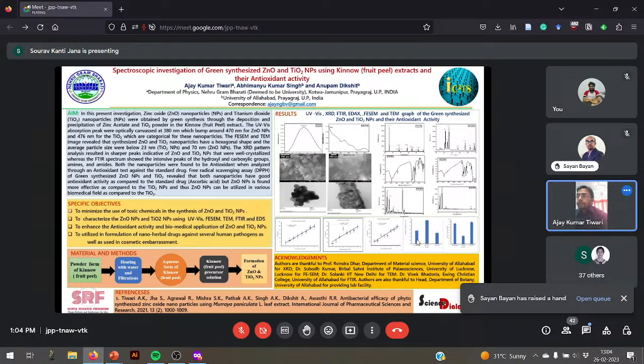Antioxidant activity. I have checked the antioxidant activity of both nanoparticles, zinc oxide nanoparticle and titanium dioxide nanoparticle, as compared to the standard drug, ascorbic acid, and found the EC50 value of the zinc oxide nanoparticle and titanium dioxide nanoparticle is mostly nearby the ascorbic acid. From the graph, we can conclude that the ARP value of zinc oxide nanoparticle is more than the titanium dioxide nanoparticle, and ascorbic acid as a standard I have taken.